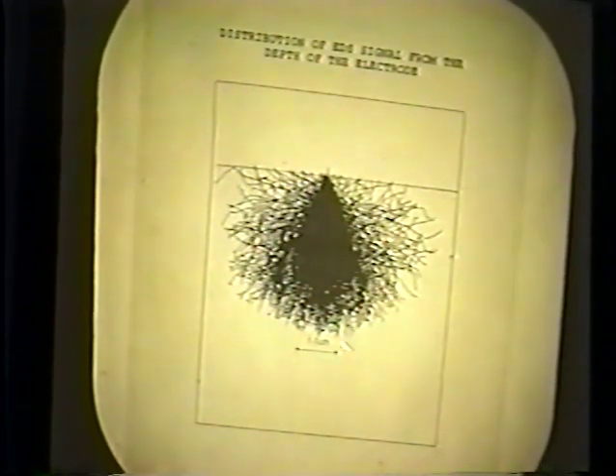But what's important here, if you see the scale here, this is 1 micrometer. Now this is 1, 2, 3, somewhere around 3 micrometers, 2 micrometers in this way. This is now different from what we had from XPS, where we had 10, 20 angstroms escape. Here we have a couple of micrometers.